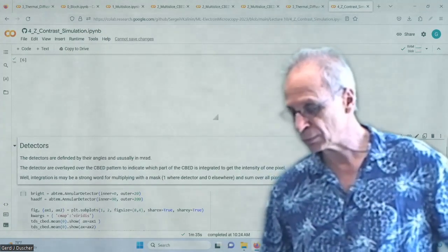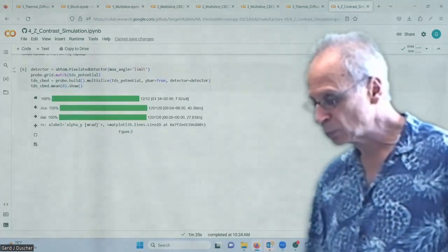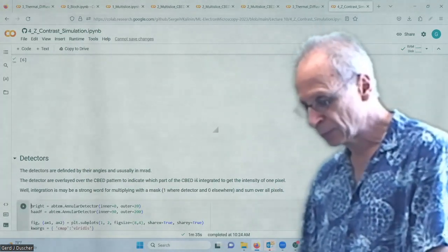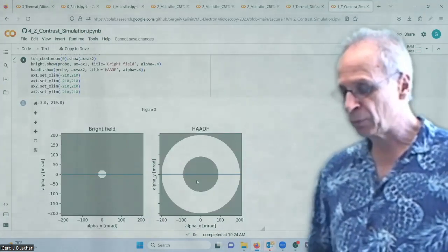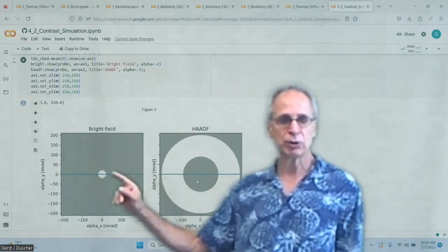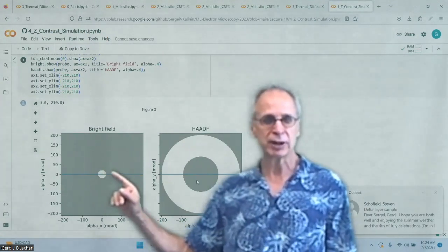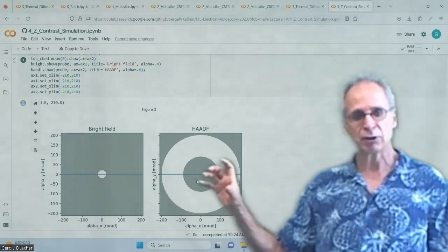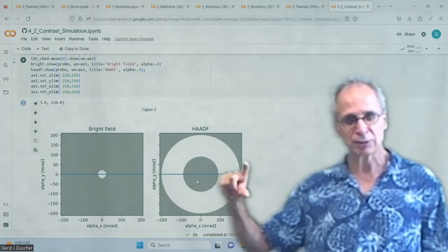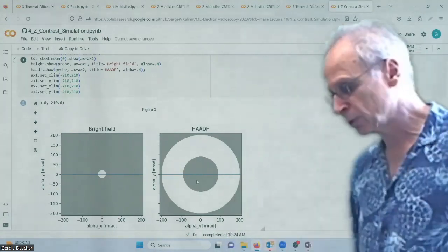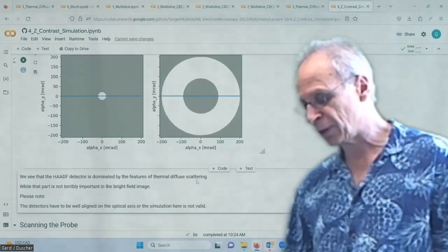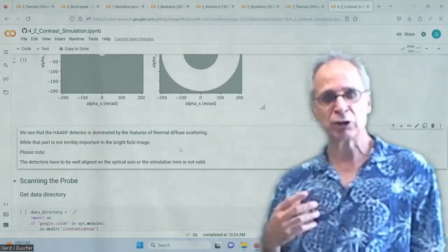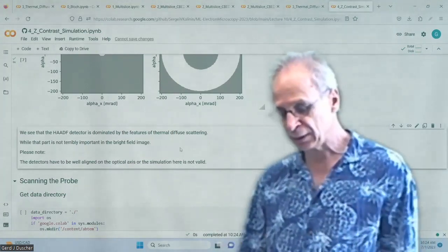The other key ingredient is different detector angles. We have ring detectors, we have cameras, we also have segmented detectors — segments of rings. That's used for differential phase contrast imaging. Again, it's a very good idea to look at what your bulk material should look like in these kinds of detectors and do your diligence here. It will take less than half an hour to make a new crystal simulation even if you haven't done it ever. We calculate our convergent beam pattern and define two detectors: a bright-field detector in the middle and the high-angle dark field detector. We can do medium-angle detectors, just a segment — four different quarters. We can define whatever we want.